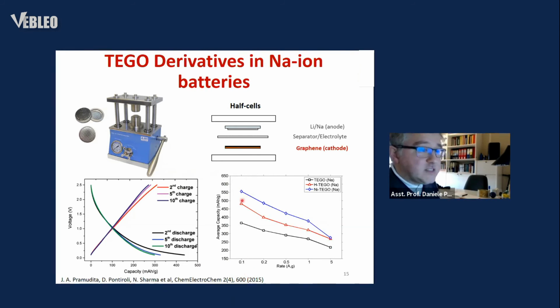As a comparison, the performance of standard graphite anode materials in lithium-ion batteries is reported here. And we can see that the peculiar voltage versus capacity slopes in graphene suggest the presence of a capacitive charge storage mechanism associated with the intercalation, which would explain the high rate capability of TEGO-based electrodes.